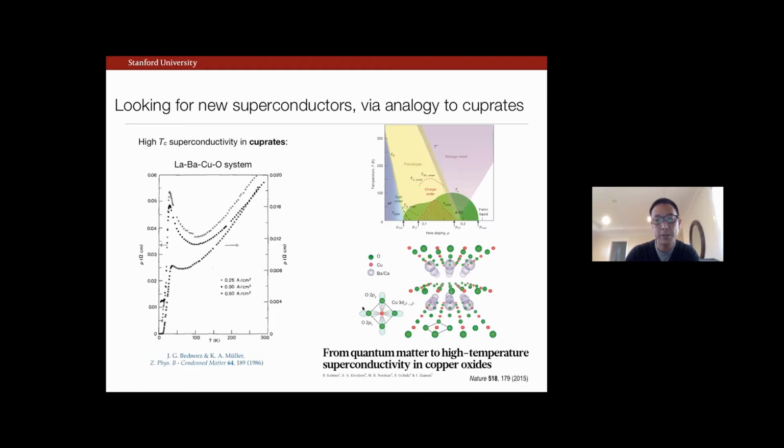I take here two pictures from a recent review article on this field, and I would like to just remind those who might be slightly less familiar that the generic motif of the system is that you start with an antiferromagnetic insulator, a correlation-driven Mott insulator. And if you dope generally holes, but in some cases electrons, into the system, you observe a dome of superconductivity. And as you can see, even at the level of a review article, this is an enormously rich and complex phase diagram with many interesting aspects of competing instabilities, for example, that are either competing or intertwined with superconductivity.